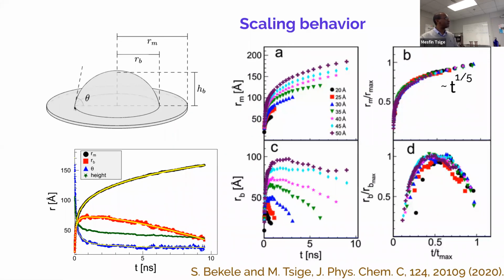So in short, this is the picture we have. I have this monolayer, I have this spherical cup. We are measuring the monolayer from the center, and this bulk from the center, and again the contact angle. For one particular droplet, this is what we see, which is common for all of them. This is what happens to the monolayer radius. We observed two different time scales. Initially it looks faster and then it slows down. This is the bulk radius of the hemispherical cup. It initially increases, then decreases. So it initially expands, then starts to shrink, and finally disappears.